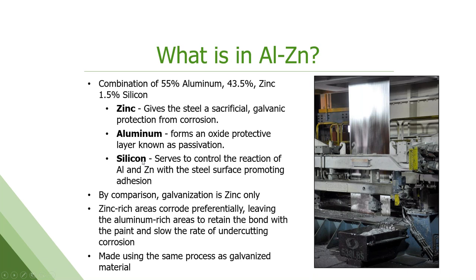And again, by comparison, hot dip galvanized is zinc only. Same process, manufactured almost the same, but it's only zinc. What happens is that the zinc areas will corrode preferentially to protect the base steel, which then leaves the aluminum areas as a protective barrier to retain the bond with the paint, if it's painted, and also the steel underneath. And that's what dramatically slows down the corrosion rate versus zinc only.